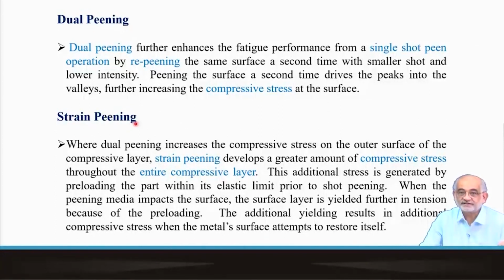As an alternative, one can even try, and this is also very effective, a strain peening operation, where the material, say a flat piece or a curved piece, has already been stretched up to the elastic limit. And now if you subject it to shot peening, then the degree of peening operation and the impact will be a lot better.